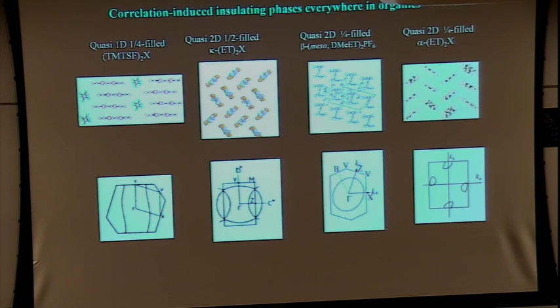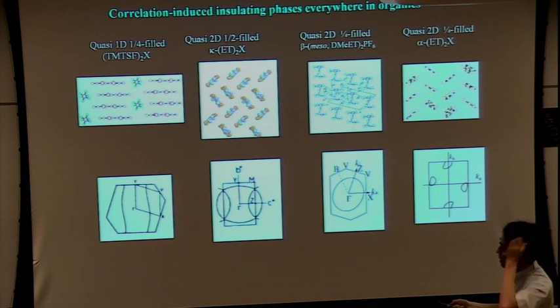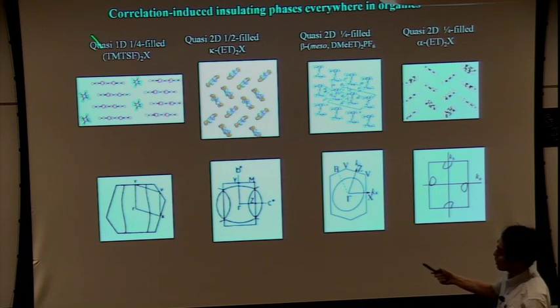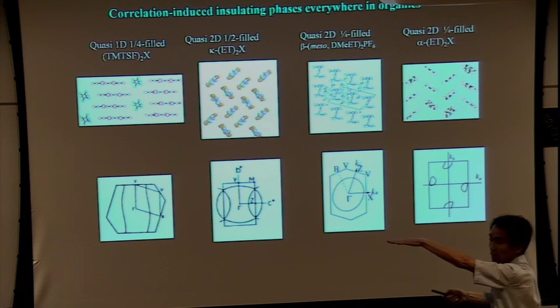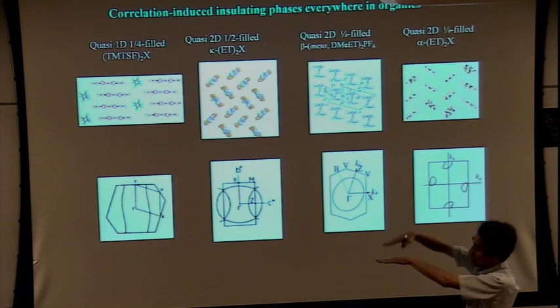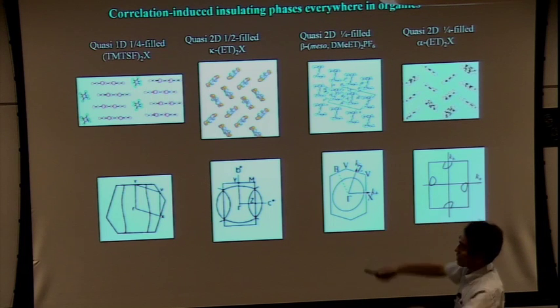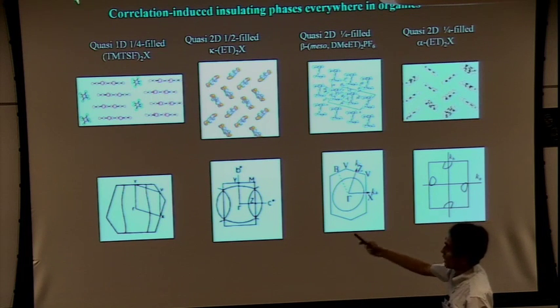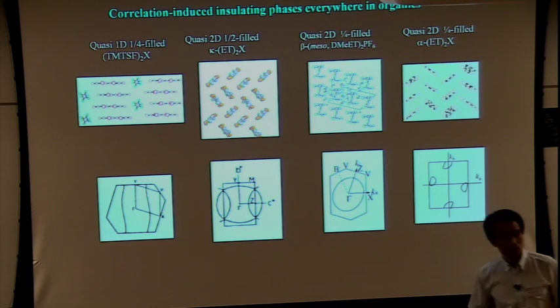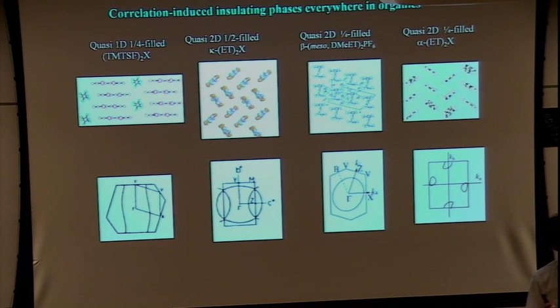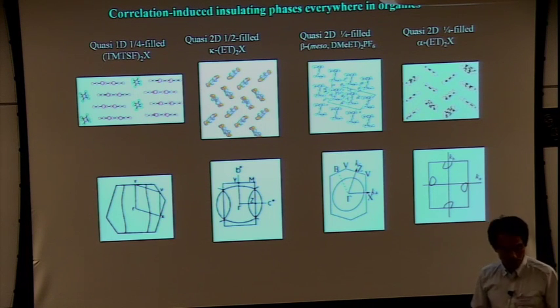Okay, so this is the band structure calculation of each material. In these materials, you can imagine a strongly one-dimensional character. This is the TMTSF molecule, like this, and these planar molecules stack in these directions. So the conductivity is very, very high in these directions, but low otherwise - the ratio of conductivity is roughly 1,000. It's a very strong one-dimensional nature.